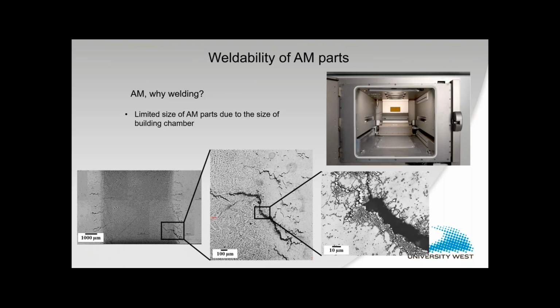I had a student who graduated during the springtime, Tahira Rasa. She's now continued to work as a lecturer here at University West. She looked into restraint as well as Gleeble testing of powder bed fusion produced alloy 718. And we could see, for instance, that it's very important that you connect the way you build the part, which will affect the grain morphology and the grain orientation of the AM part, that you think of the build direction as well and connect that to the weld preparation later, because the grain orientation and the grain size significantly affect the weldability of the material.